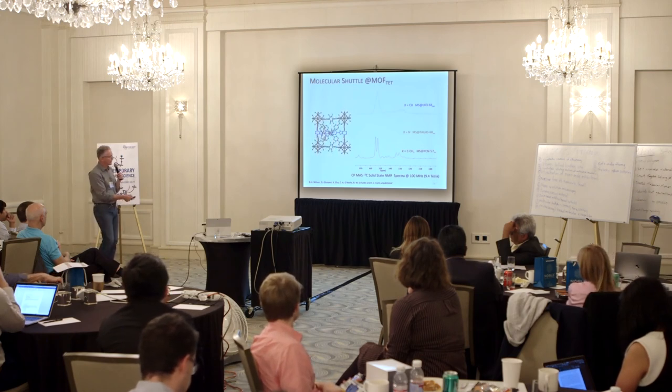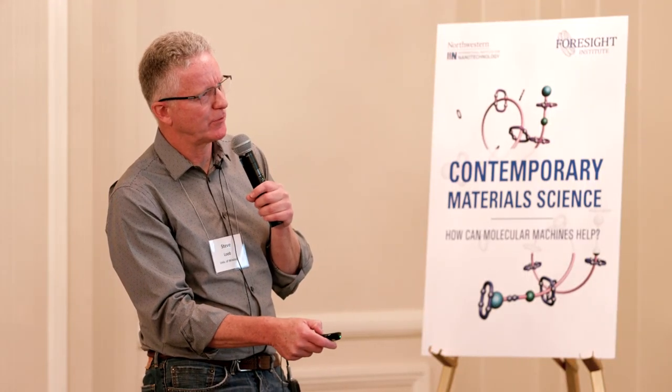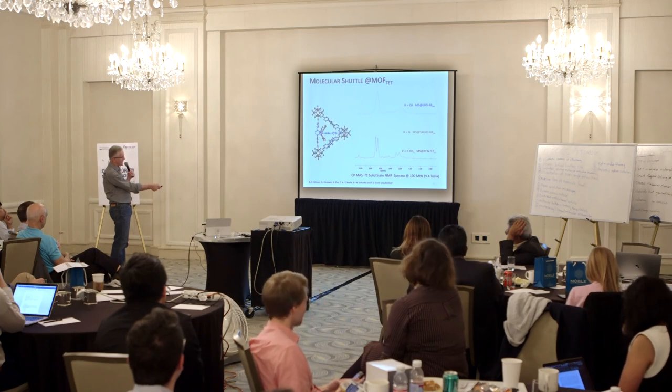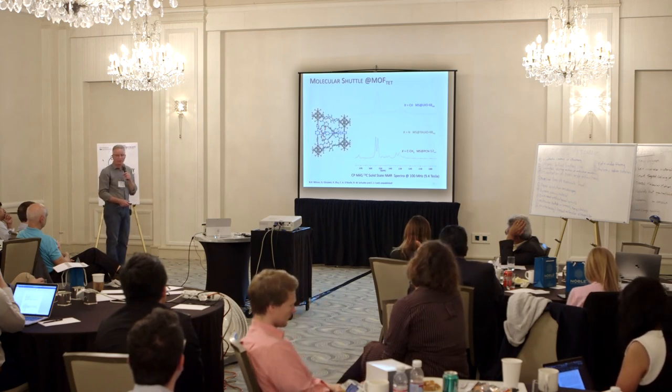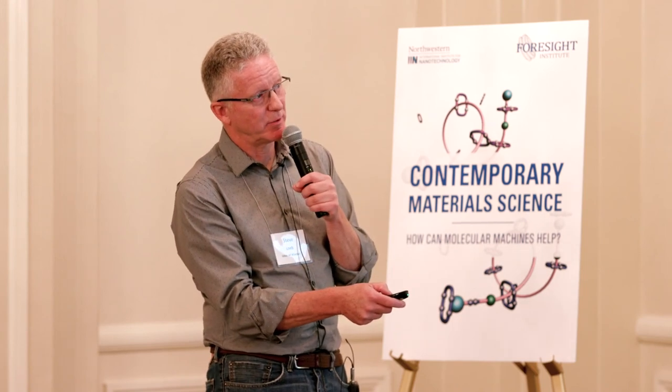So the case where there's four nitrogens, I don't have the spectrum here because my postdoc forgot to send it to me, is moving fast. So when you put the nitrogens, this ring rotates and it becomes in the plane and there's nothing to block, okay? And then the cool part is, if you just have CHs here, where this ring can probably rotate, it's in between. So this one is flat. It's almost at coalescence at room temperature. This one's not moving. This one's moving fast. And this one's moving somewhere in between. And so the one is locked.